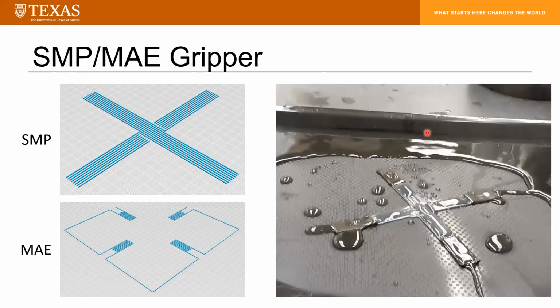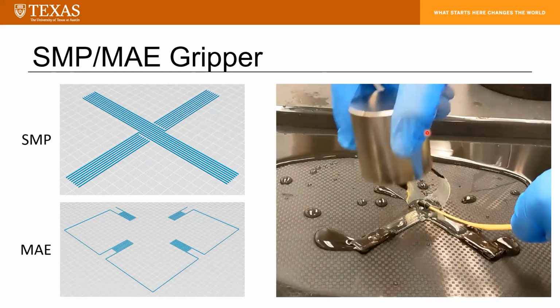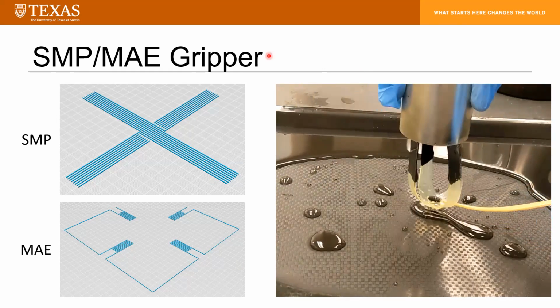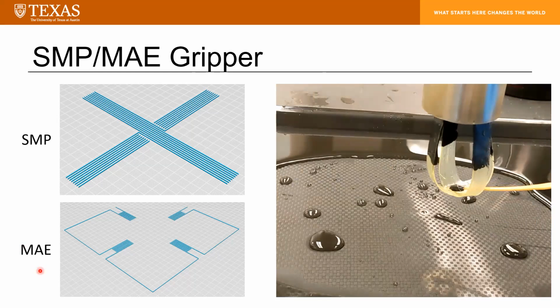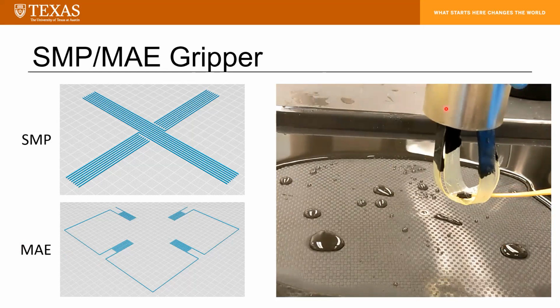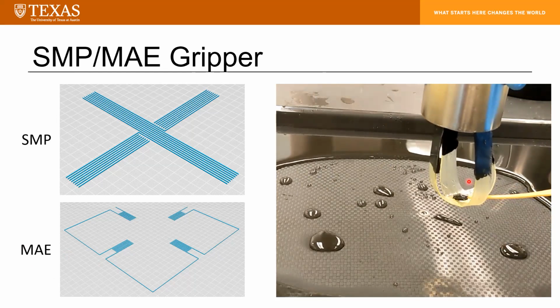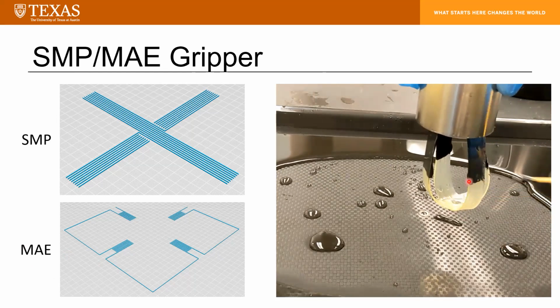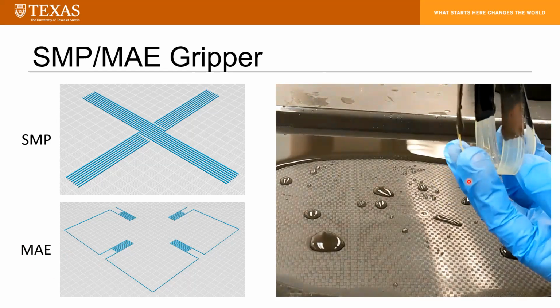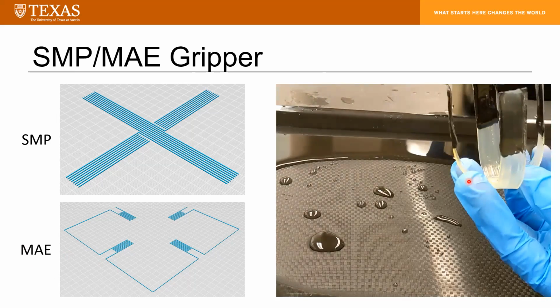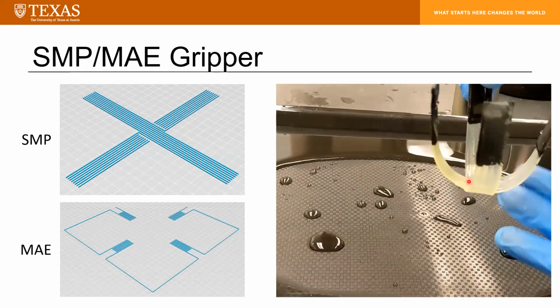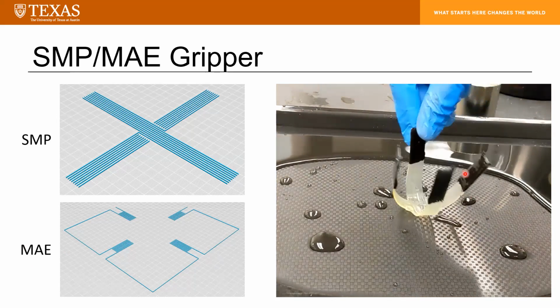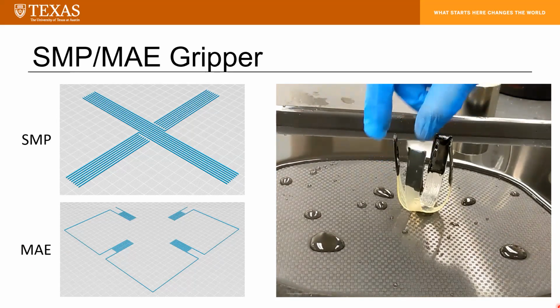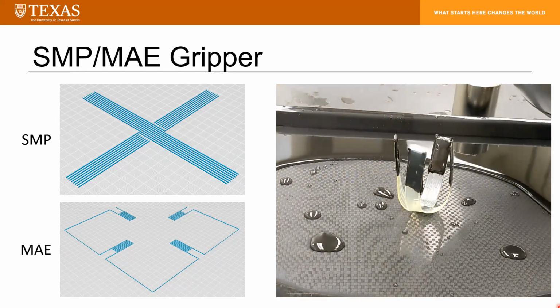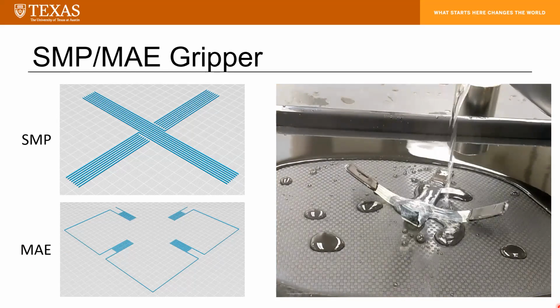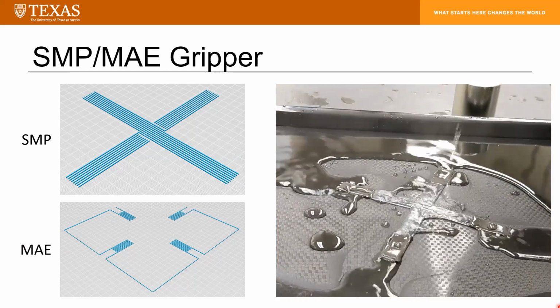So what we've done is we've created a multi-material composite consisting of a shape memory polymer backbone over here, the SMP, with a magnetically active elastomer, an MAE, placed at the edges. So what I've done is I've heated up the SMP with a splash of hot water that you saw at the beginning of this video. I'm shape programming it now. I'm holding deformation. It has since cooled, locking in our temporary shape. Let me move my laser a little bit. There you have it. And then now I will return to the as manufactured shape by again heating up the part with hot water. And as you can see, the return is rather speedy.